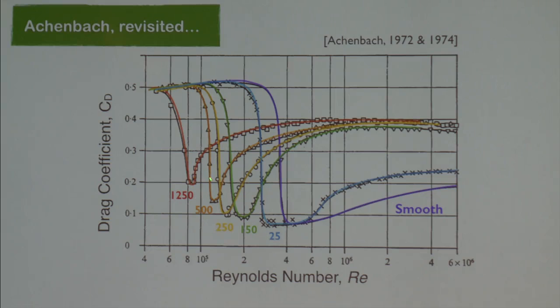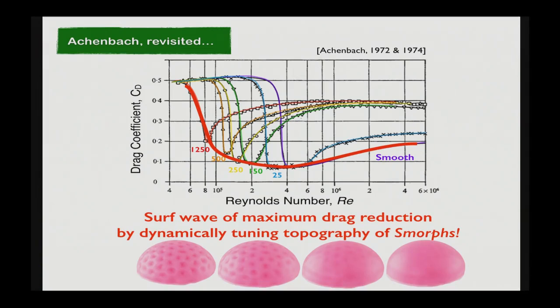At lower wind speeds, the rougher the ball, the better. So by having an active surface, depending on the wind conditions, we're able to actively tune on demand the roughness of our surface. By knowing where you are, we can actually ride the surface of minimum drag. So you're able to get a surface with lower drag by being active than any other static surface. And I think this is exciting, and we're very actively pursuing this right now in our lab.